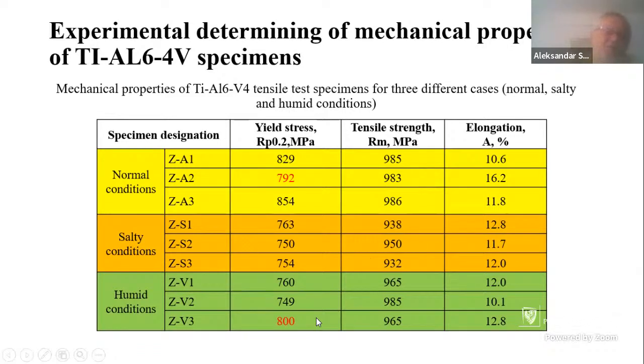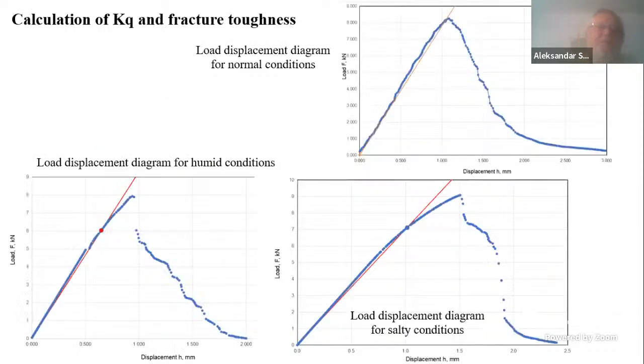And then again, for humid condition, of course, you might expect some discrepancies of results. But in any case, it's clear that normal condition has the best tensile properties, and humid condition is somewhat better than salty condition. Not a big difference, though, one should notice even at this stage.